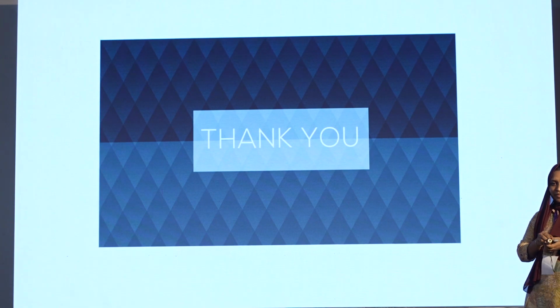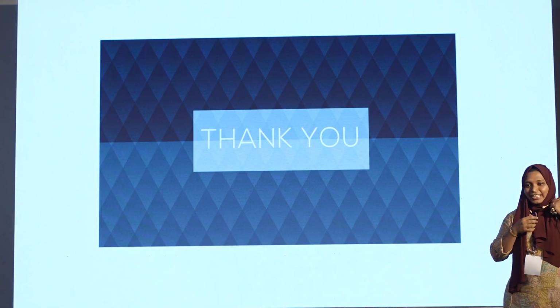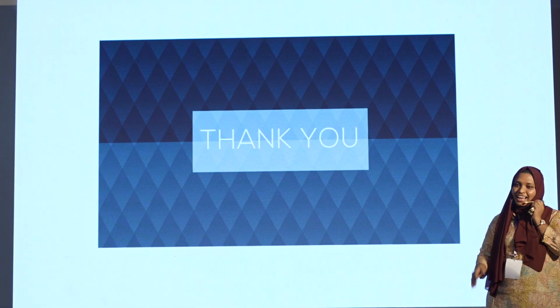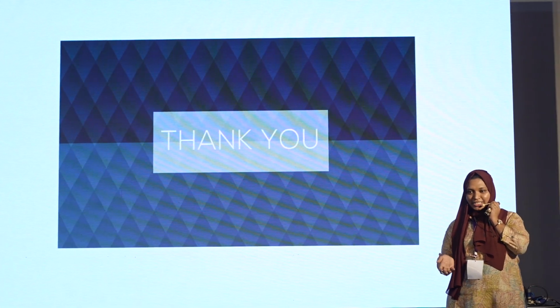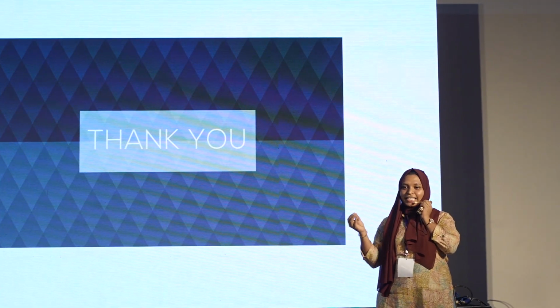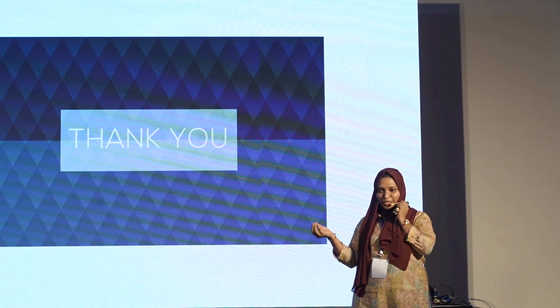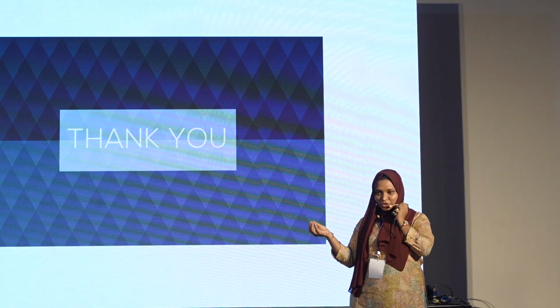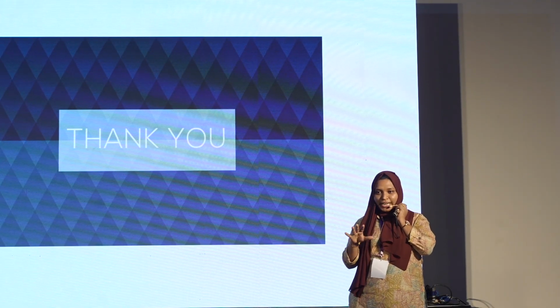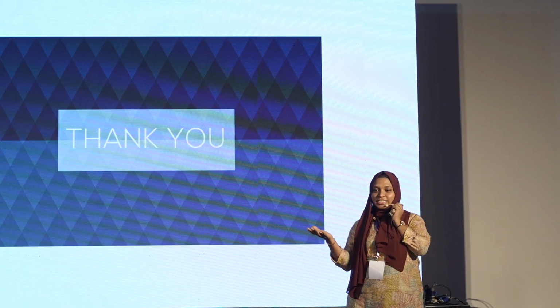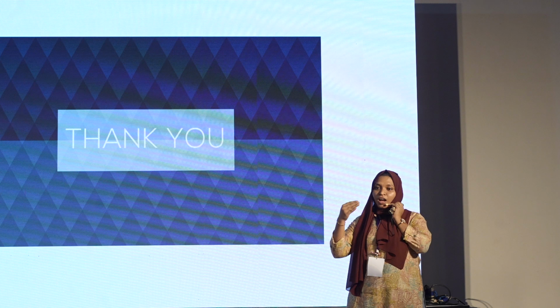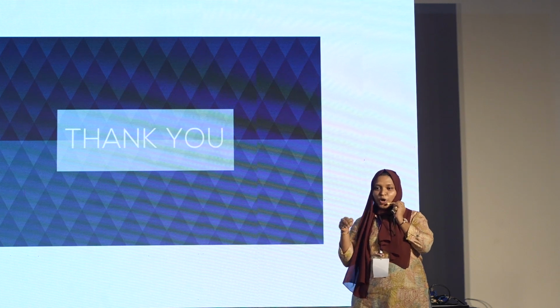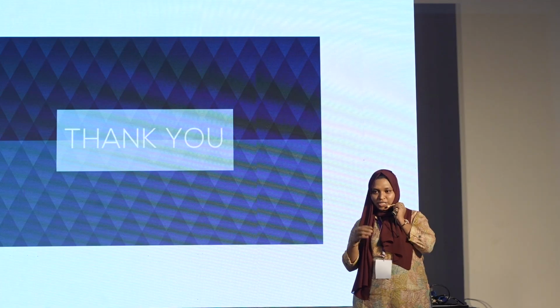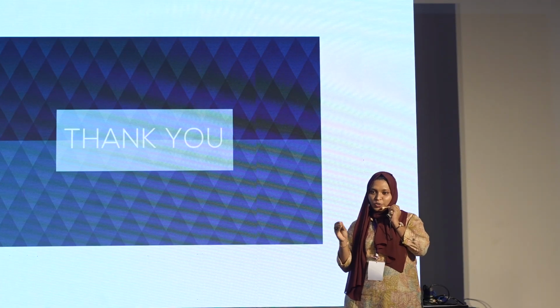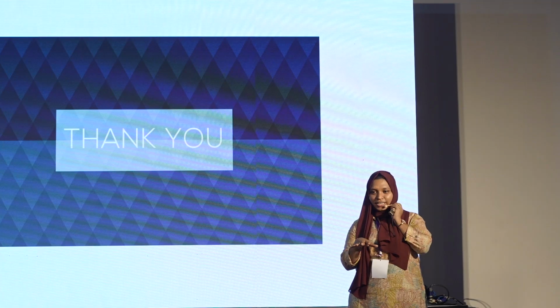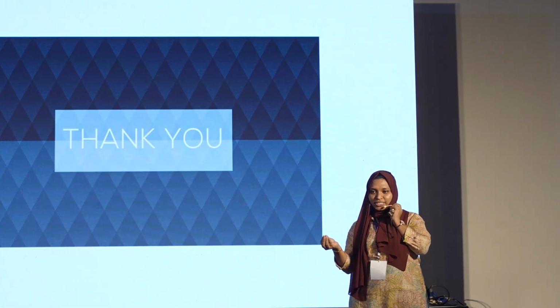Why not selenium? Both tellurium and selenium can be chosen. Our team is now working on selenium as well. But we were impressed by the positive electrode potential of tellurium, that is, around 0.8 electron volt. So we can do polymerization without the aid of any external oxidants or reducing agents. Solely EDOT and Te4+ ions undergo redox reaction, and this is an in situ process where TeNPs would get embedded in the PEDOT matrix. So minimal use of reagents can be done here.